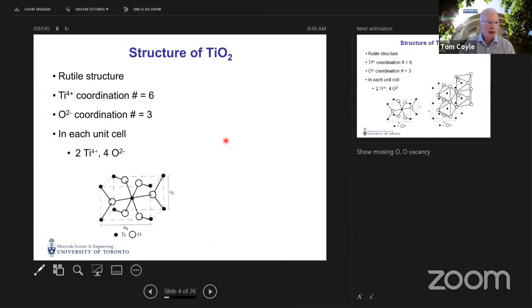So TiO2, an ionically bonded oxide, crystallizes in the rutile structure, where in the perfect structure, the titanium ions have a +4 charge and are coordinated with 6 oxygen. 4 of those oxygen are equidistant from the central titanium atom, and 2 of those oxygen atoms are at a little bit longer distance. Each unit cell contains 2 titaniums and 4 oxygen.